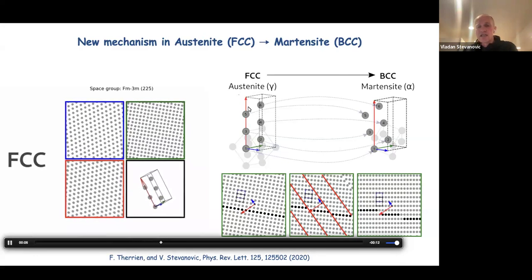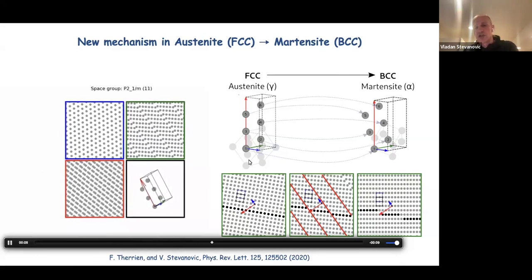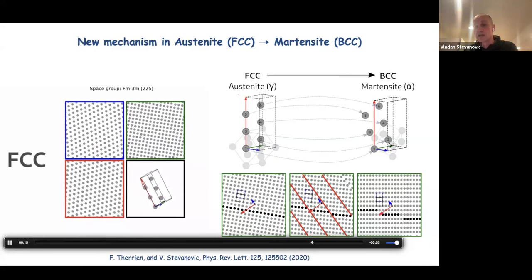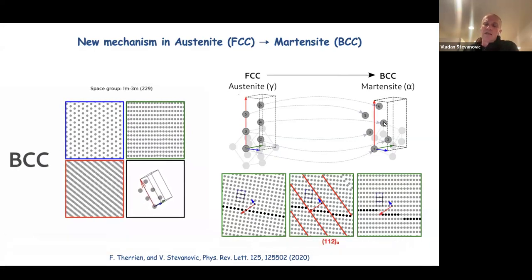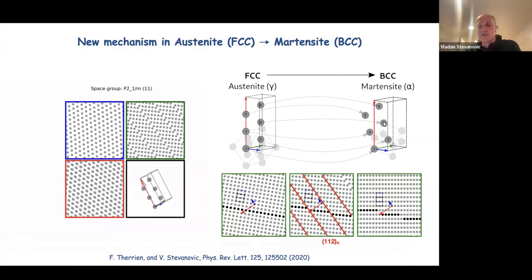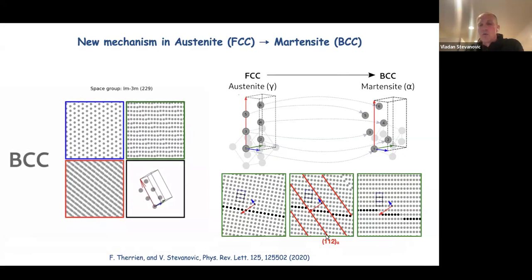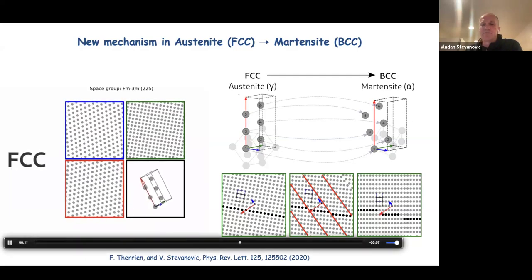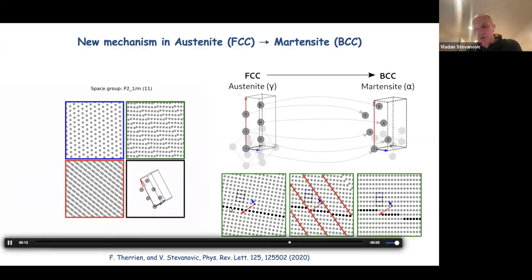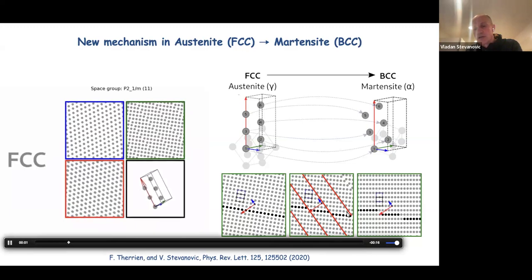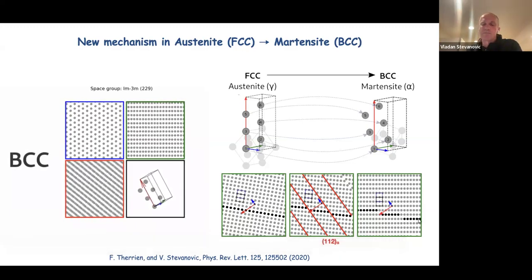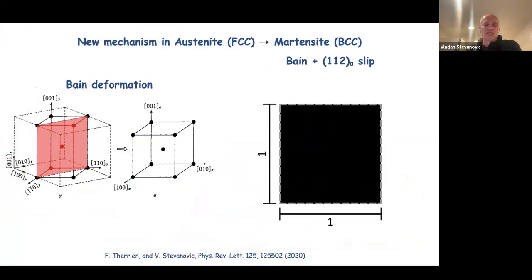So a little bit better picture is then shown in the right panel, a more detailed, not a better, picture, where you can see exactly the box in relation to the conventional unit cell that is shown in a lighter color, and then the mapping. So atoms are indexed based on the mapping. And then you can ask, okay, fine, but what is then the direction of this slipping process? So the slipping process can be described by the Miller vector 112 expressed in the BCC basis. And you can see what the slipping actually produces. So this plane that is shown highlighted in black basically breaks down due to the slipping process.